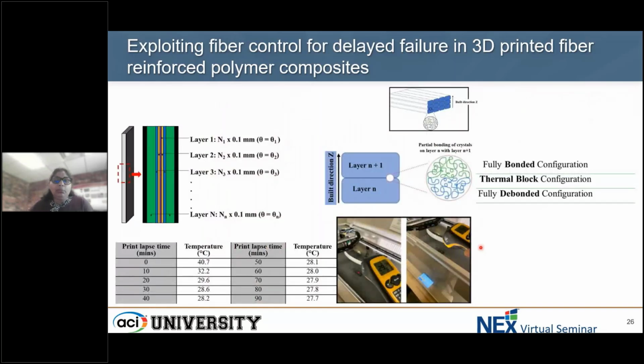If you consider a thermal block configuration, what we did is, since cooling and heating environments really affect polymerization and the ability of layer welding, which is basically welding the layer that has been deposited with the layer that will be deposited. So layer N, which has been deposited, needs to weld with layer N plus 1. For that, temperature requirements and the print chamber conditions are a must. In order to create that alternative bond between these two layers, we affected the interface between layer N and layer N plus 1.